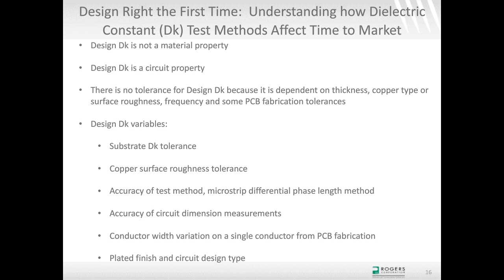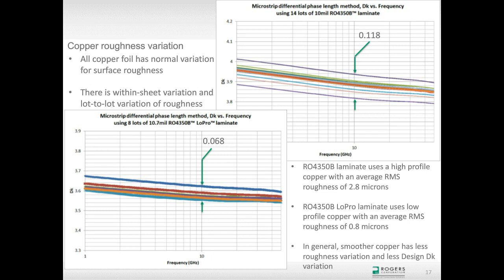And I'll give you an example of something we did similar. This is actually for a different reason, but it's kind of giving the same idea that we're trying to figure out what the range of the design Dk is. In this particular case, what I was doing, though, was something a little different. And we know that the copper surface roughness does vary. It's not always the same number. So when we get a high-profile copper that's used on the standard RO4350B laminate, that copper has an average roughness of 2.8 microns RMS, but it does vary up and down some. And we know that the variation of copper surface roughness will vary the design Dk.